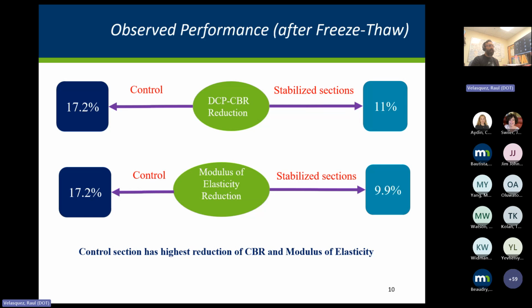So in terms of mechanical performance, stabilized sections, after being subjected to a freeze-thaw cycle, after going through a winter and a spring cycle, show positive results in the sense that performance has been reduced less when you have stabilizers. Basically, for shear strength measured using DCP, the reduction in performance for the control sections is about 17.2% on average, where the stabilized sections only have a drop in performance of about 11%. In terms of stiffness measured by the LWD device, again, the control sections show a reduction after going through a freeze-thaw cycle of about 17%, while the stabilized sections have a reduction of 9.9%. So there are some positive results regarding mechanical performance.